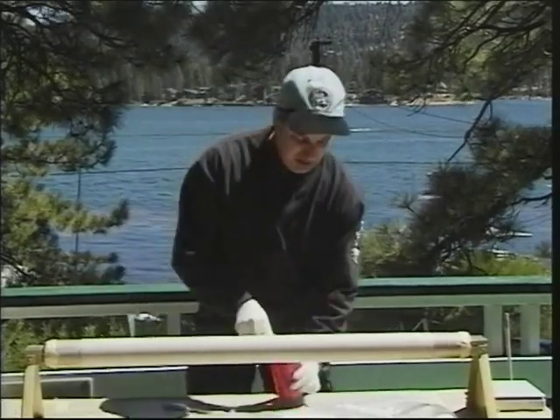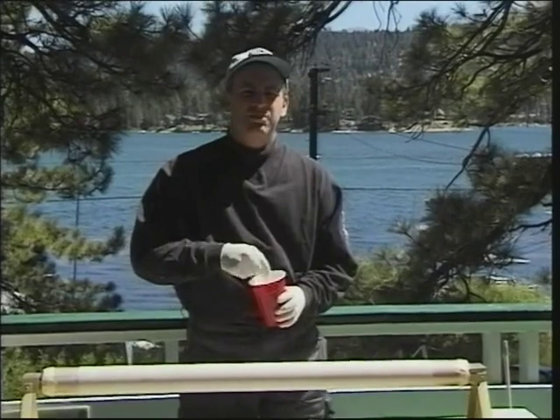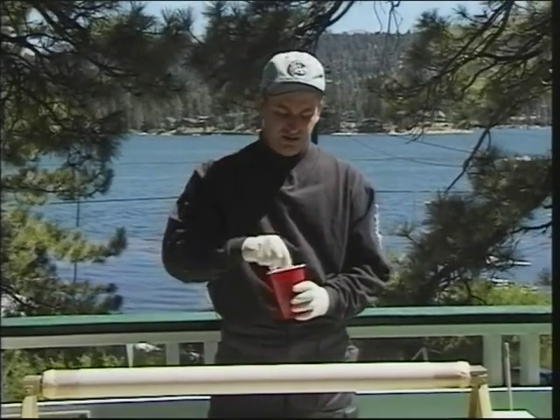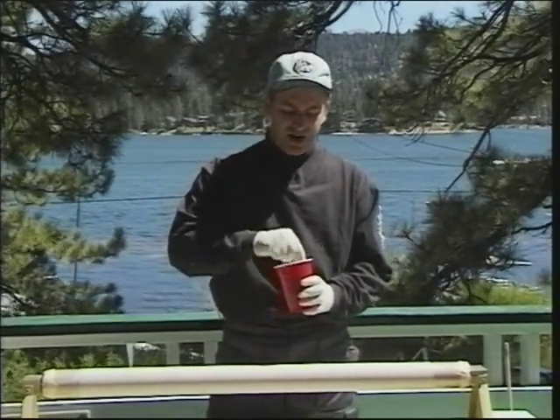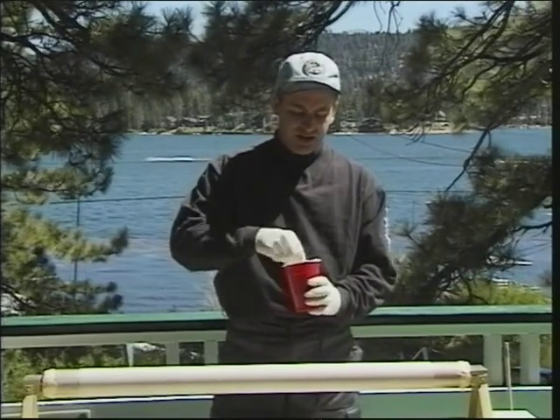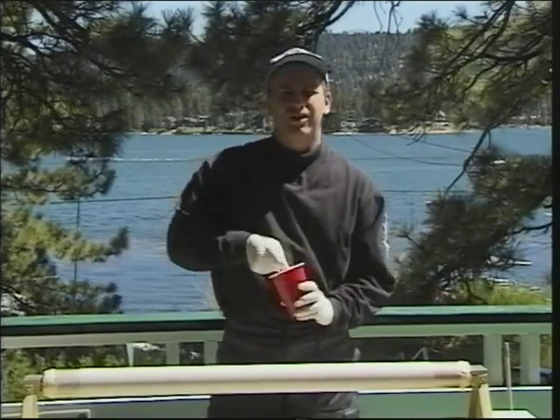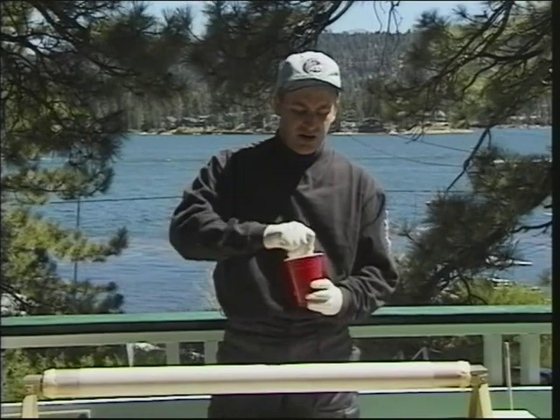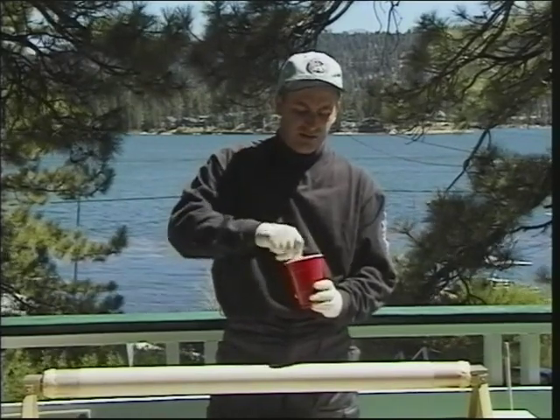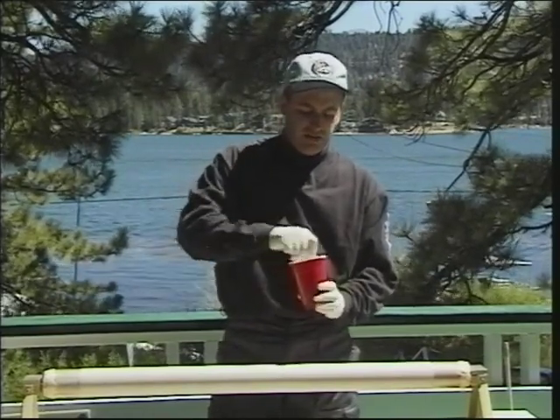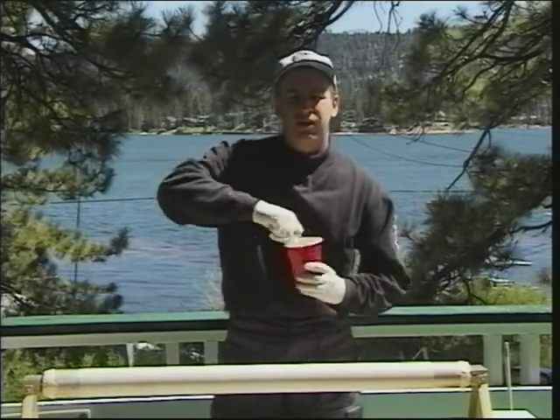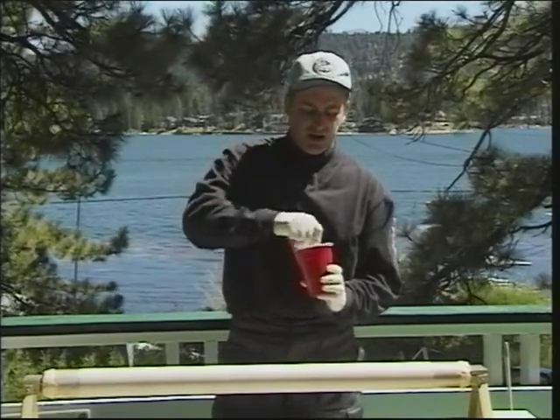And then mix it very well. Any parts of hardener that aren't mixed in with resin are essentially going to leave a soft spot of resin. So make sure the hardener is very well incorporated with the resin. You can whip it up real good, scrape all the sides of the cup, and get it going.